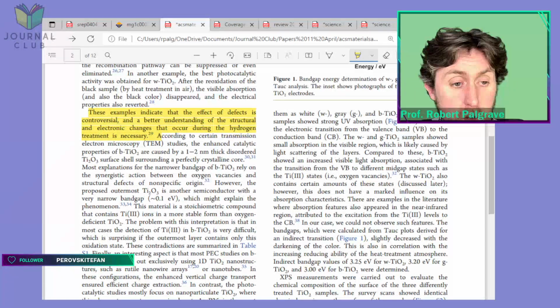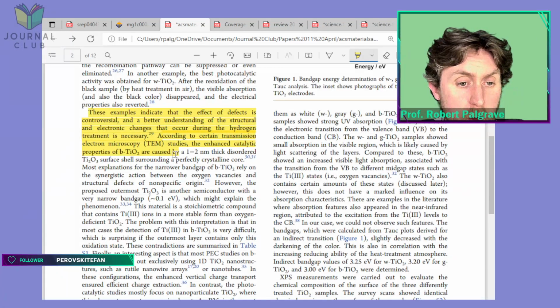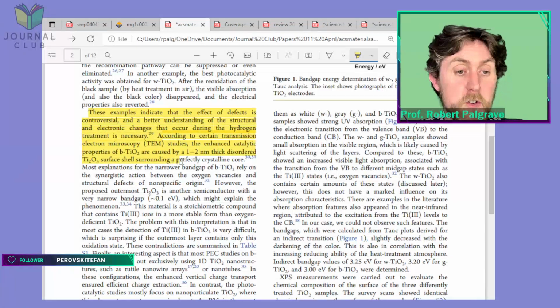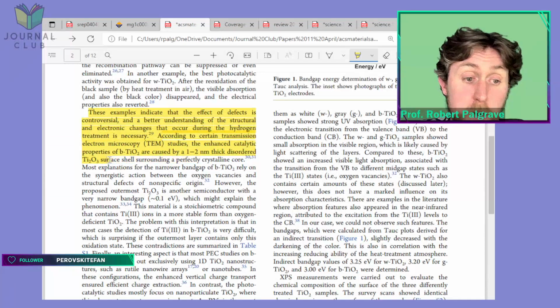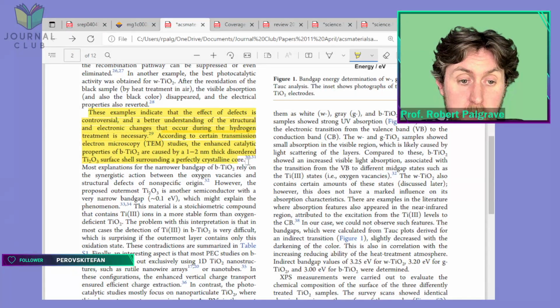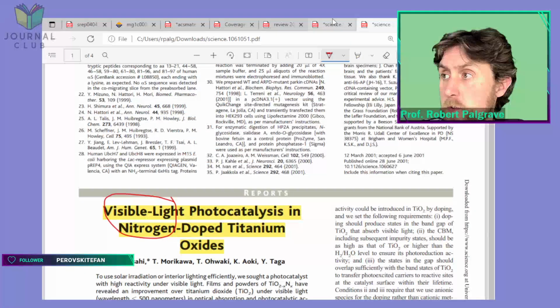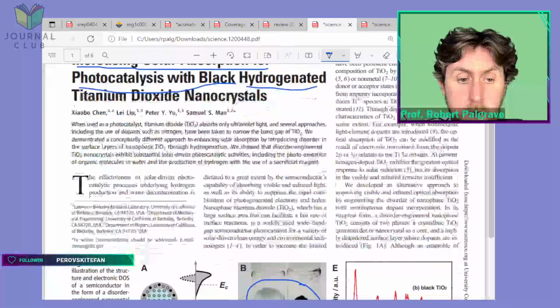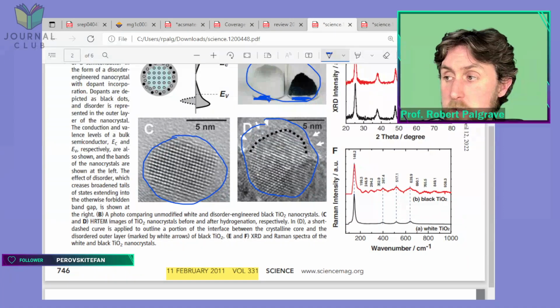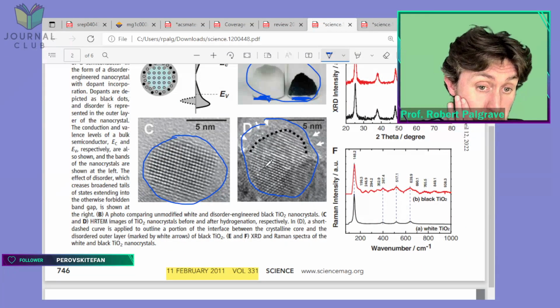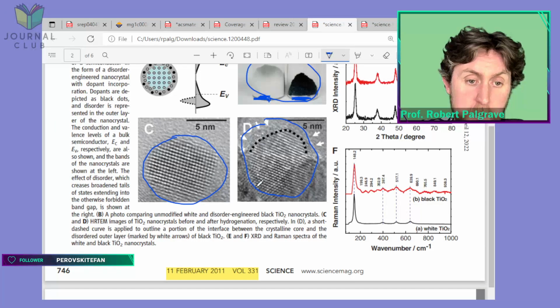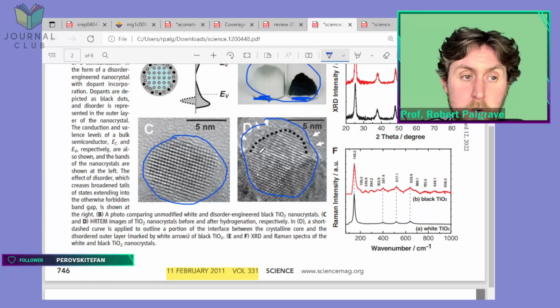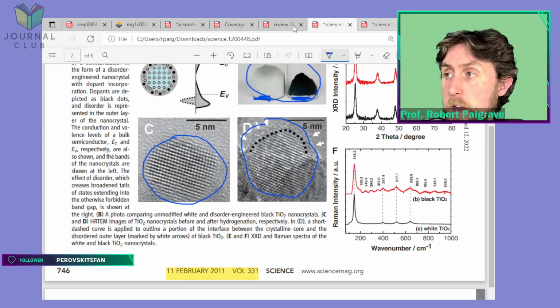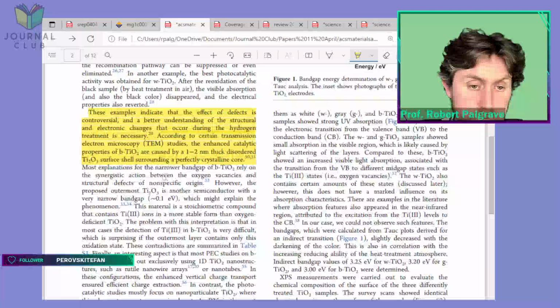Okay, according to certain transmission electron microscopy measurements, which I just showed you a minute ago, the enhanced catalytic properties of black TiO2 are caused by a 1 to 2 nanometer thick disordered TiO2 surface shell surrounding a perfectly crystalline core. Okay, so if we go back to the original paper that I showed you a second ago, this is one such TEM image. So here you have your crystalline core, here you have your amorphous or poorly crystalline layer around that. Right, back to here anyway.